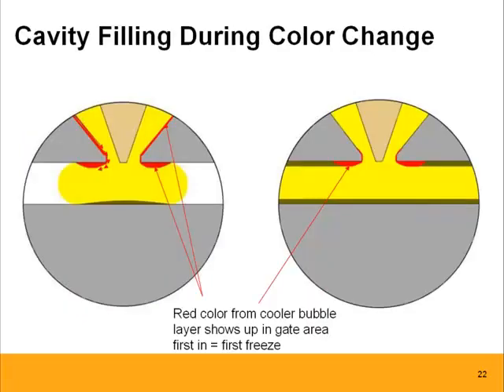And why do we want to flush out that bubble? This is just the example again, a little bit more blown up. Because of the laminar flow of the resin, while we have pretty much changed the material over, the former red material sort of clings to the outer surface, and therefore, from a visible point of view, when we do color changes, we always see the streaks on the top surface of the part. Of course, then these parts become scrap, because that's not something that you as a customer can sell to your customers.